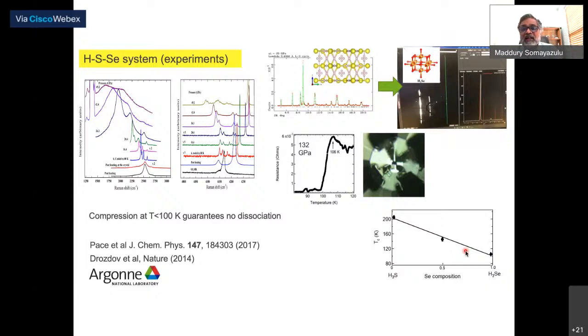So in other words, it's all based, of course, on transport measurements. And this is an example of a transport measurement I'm showing you, where you see a transition temperature of about 106 Kelvin at about 132 GPa in selenium hydride. Now, what it tells you is that you could do these kind of directed measurements and possibly understand the complexation involved in looking at systems which are more than just binary systems.